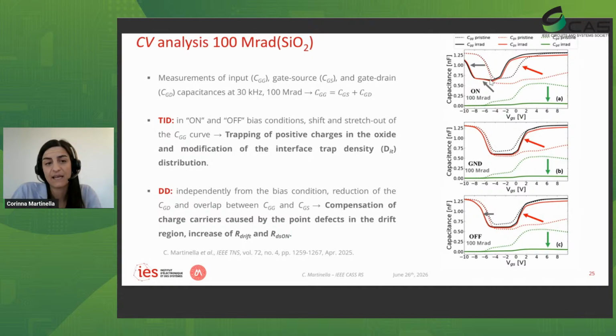And then the displacement damage shows its impact by completely reducing the gate drain capacitance. So there is no more capacitance, it's no longer capacitive there, our component. The gate drain capacitance after irradiation is totally flat, and the gate source capacitance is just equal to the input capacitance. We can see that as well for the device irradiated in ground condition. Here we don't have TID effect, we only have displacement damage, and we can see how there was the drop, the modification of these two curves.